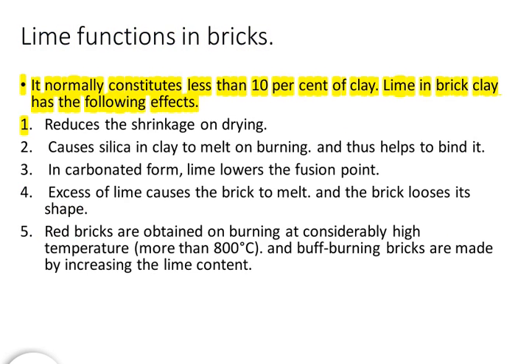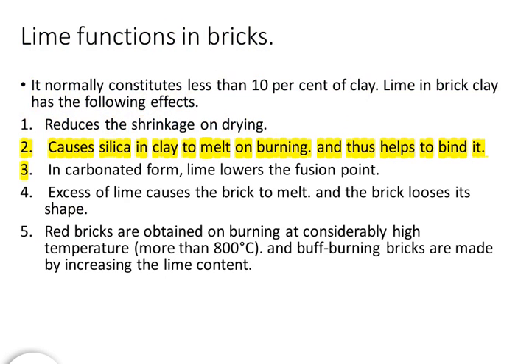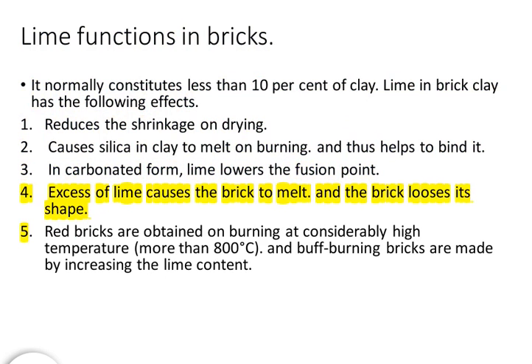Lime functions in bricks. It normally constitutes less than 10% of clay. Lime in brick clay has the following effects: 1. Reduces the shrinkage on drying. 2. Causes silica in clay to melt on burning and thus helps to bind it. 3. In carbonated form, lime lowers the fusion point. 4. Excessive lime causes the brick to melt and the brick loses its shape. 5. Red bricks are obtained on burning at considerably high temperature more than 800 degrees Celsius, and buff-burning bricks are made by increasing the lime content.